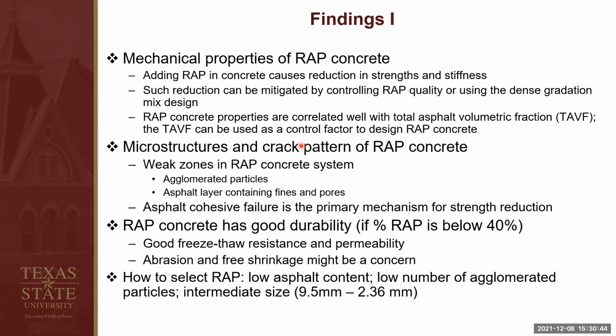However, we found such a reduction in strength and stiffness can be more mitigated by controlling RAP quality and also by using the dense gradation mix design. And we also found RAP concrete properties are correlated very well with the total asphalt volumetric fraction, so that we can use the asphalt volumetric fraction as a control factor to design RAP concrete to achieve adequate strength and